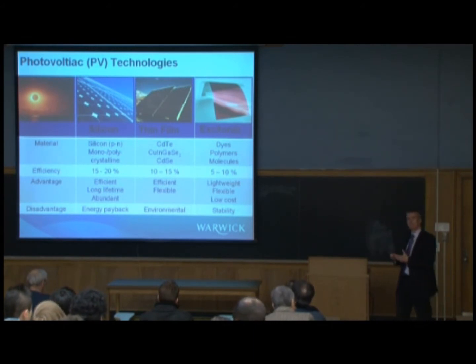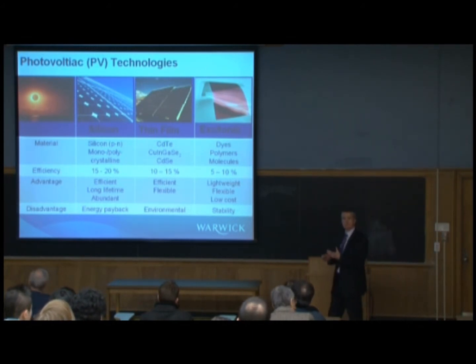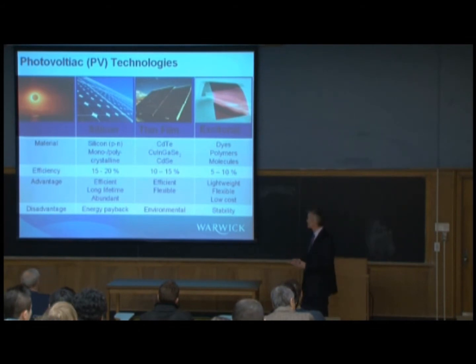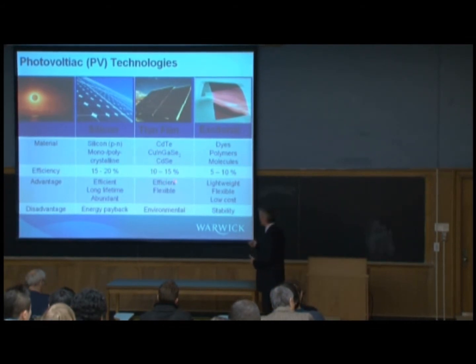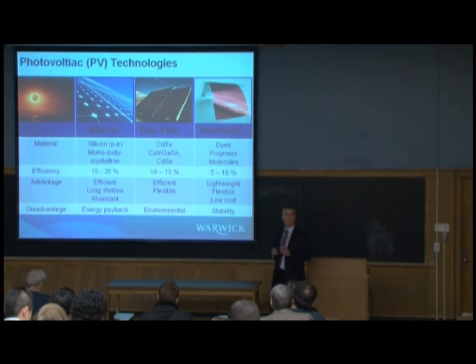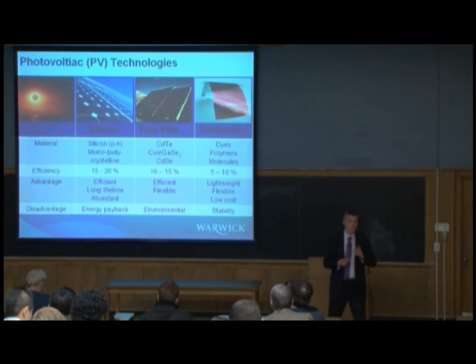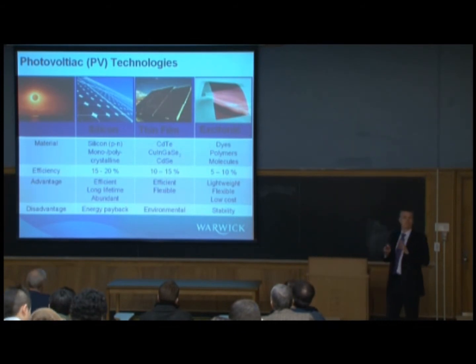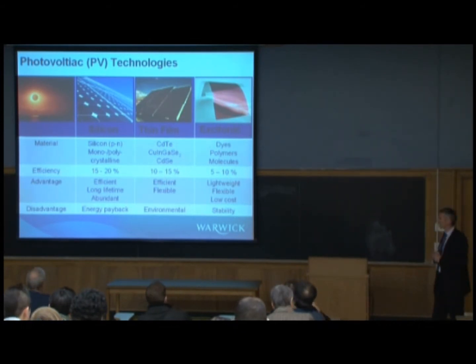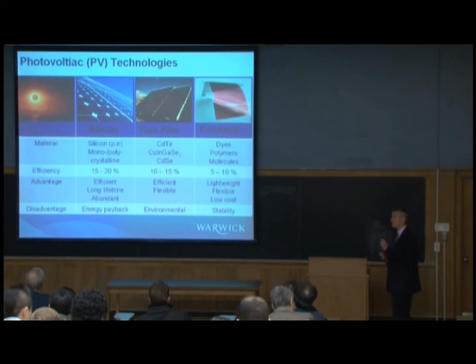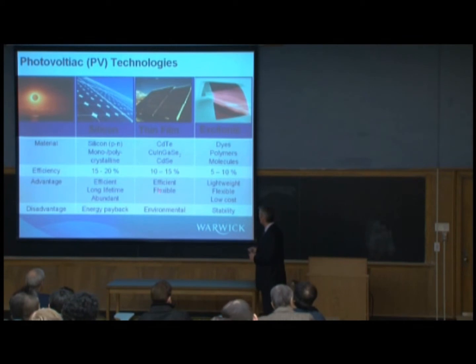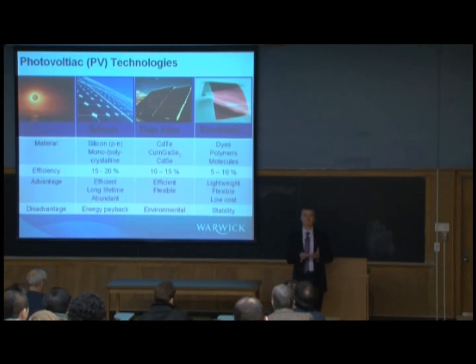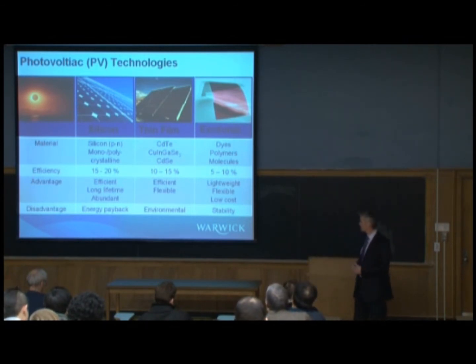But because of that process, the crystalline quality of the material is poorer. There are more defects, and generally the performance goes down. So the best performances are in the 10 to 15% bracket. Still pretty good, and indeed there's a reasonable number of thin film solar cells sold commercially and installed for power generation applications. So fairly efficient, can be put on flexible substrates, so that's certainly a plus. But again, market penetration, it's still a subsidized industry, so it's still too expensive.